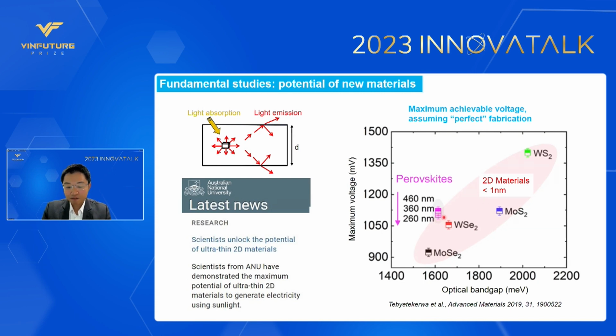These are the data for perovskite material with different thicknesses of hundreds of nanometers, a very hot topic now, and different two-dimensional materials with a thickness of less than 1 nanometer. For two-dimensional materials, usually there is no well-defined thickness because they have only a few layers of atoms or molecules. We cannot measure the thickness precisely.